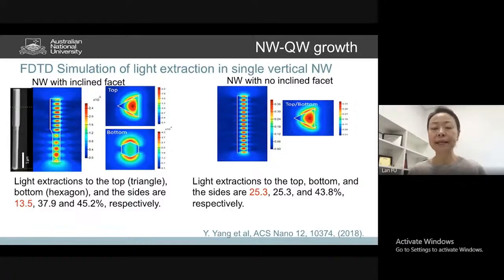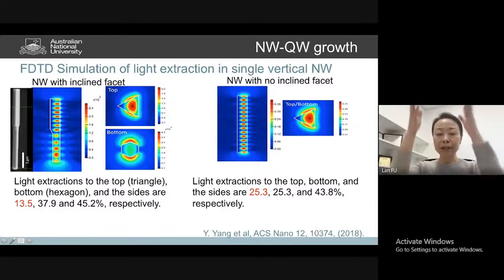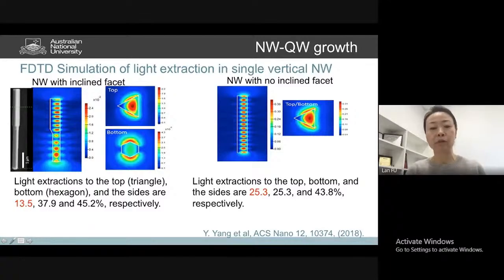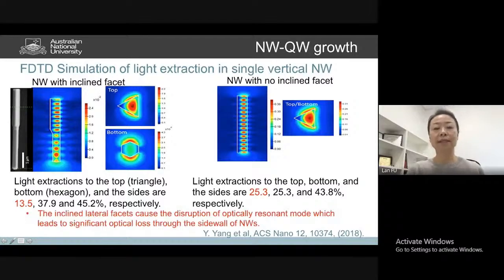I'm not going into the details of the simulation, rather just saying that if we have this inclined facet, non-uniform morphology, the light extraction on the top triangular is actually quite low. But if we have rather uniform morphology, even with this triangular shape, you have probably about double that light extraction. And this is because this inclined facet basically causes disruption of the optical resonance that leads to some optical loss. That's the reason.